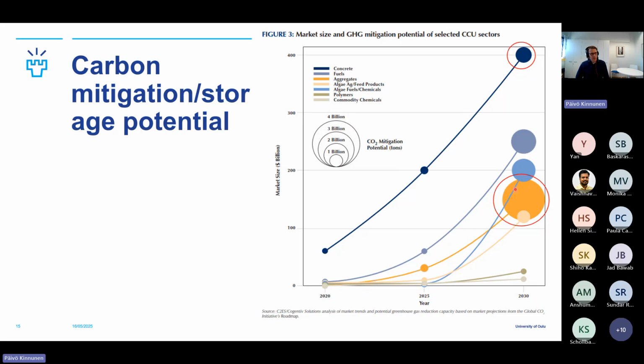But what's also evident is that the market size is much smaller. And of course, we also have to take into account that the reason for using aggregates is precisely because of their low cost, and so it's only some euros per ton of material, and usually the transportation becomes an issue already after, let's say, 50 kilometers. So it is not as simple as just replacing the material.